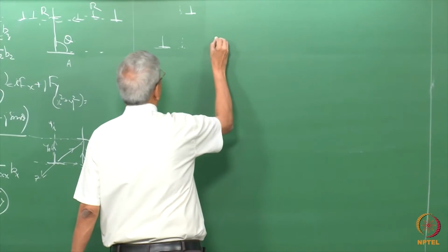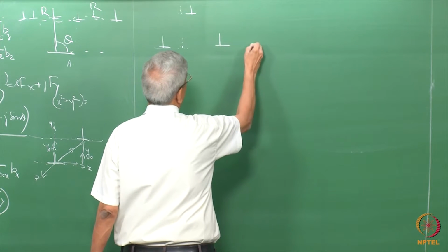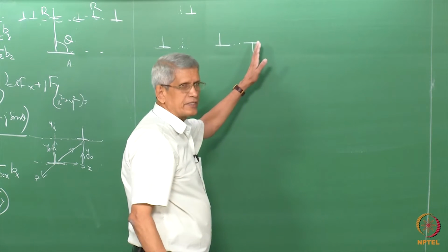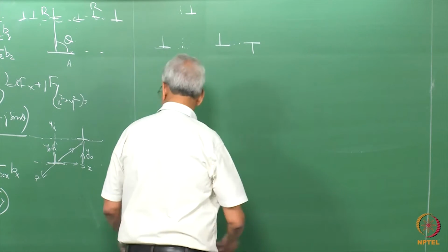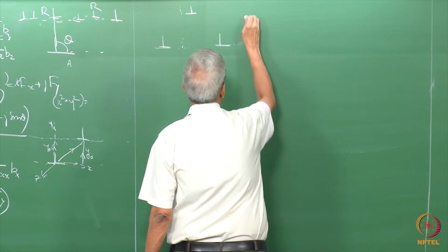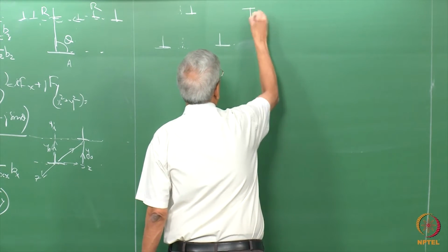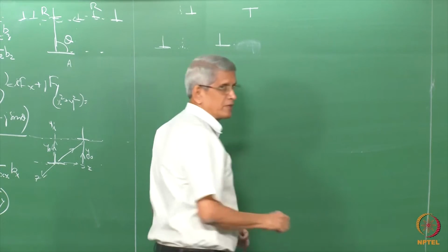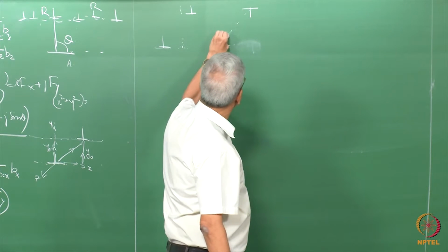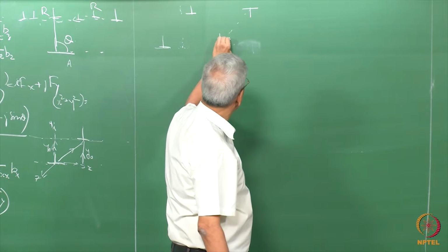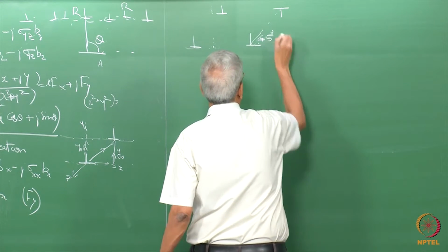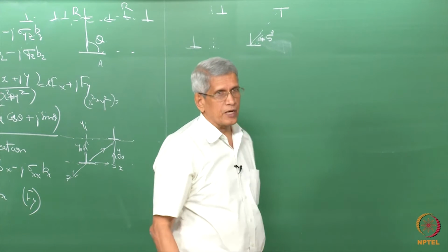Suppose a dislocation in the same slip plane is there, these will attract each other and cancel. The other case is that instead of that, this dislocation is going to be here. Now when these dislocations are making an angle of 45 degree, this is going to be a minimum energy configuration.